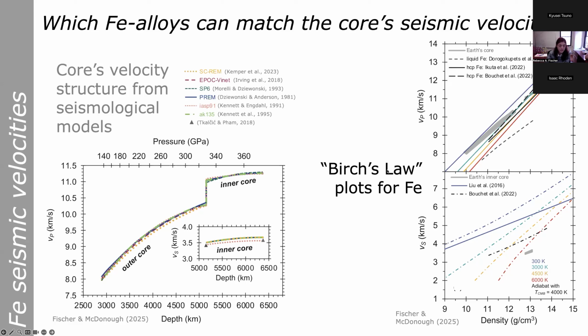In particular, if we look at the inner core, it has a rather high Poisson's ratio, the Poisson's ratio being a measure of the VP to VS ratio. So in other words, the Earth's inner core has a high VP and a low VS compared to what we would expect for pure iron at the same conditions.